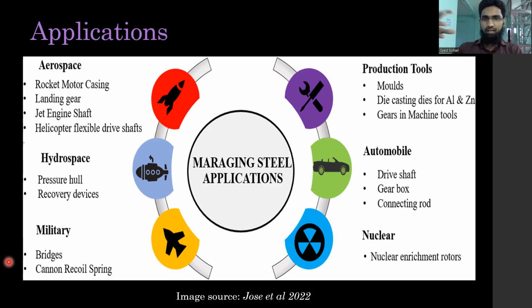Either the die breaks. It is a low alloy steel, high strength die, let's say. But it breaks because of some unstable fracture that is propagated, some unpredictable failure that has happened, corrosion, hydrogen embrittlement, some other issue. Now there will be delays in the production schedule and there will be additional expenses. So this will reflect on your productivity. So this is why I said it makes up for the higher costs.